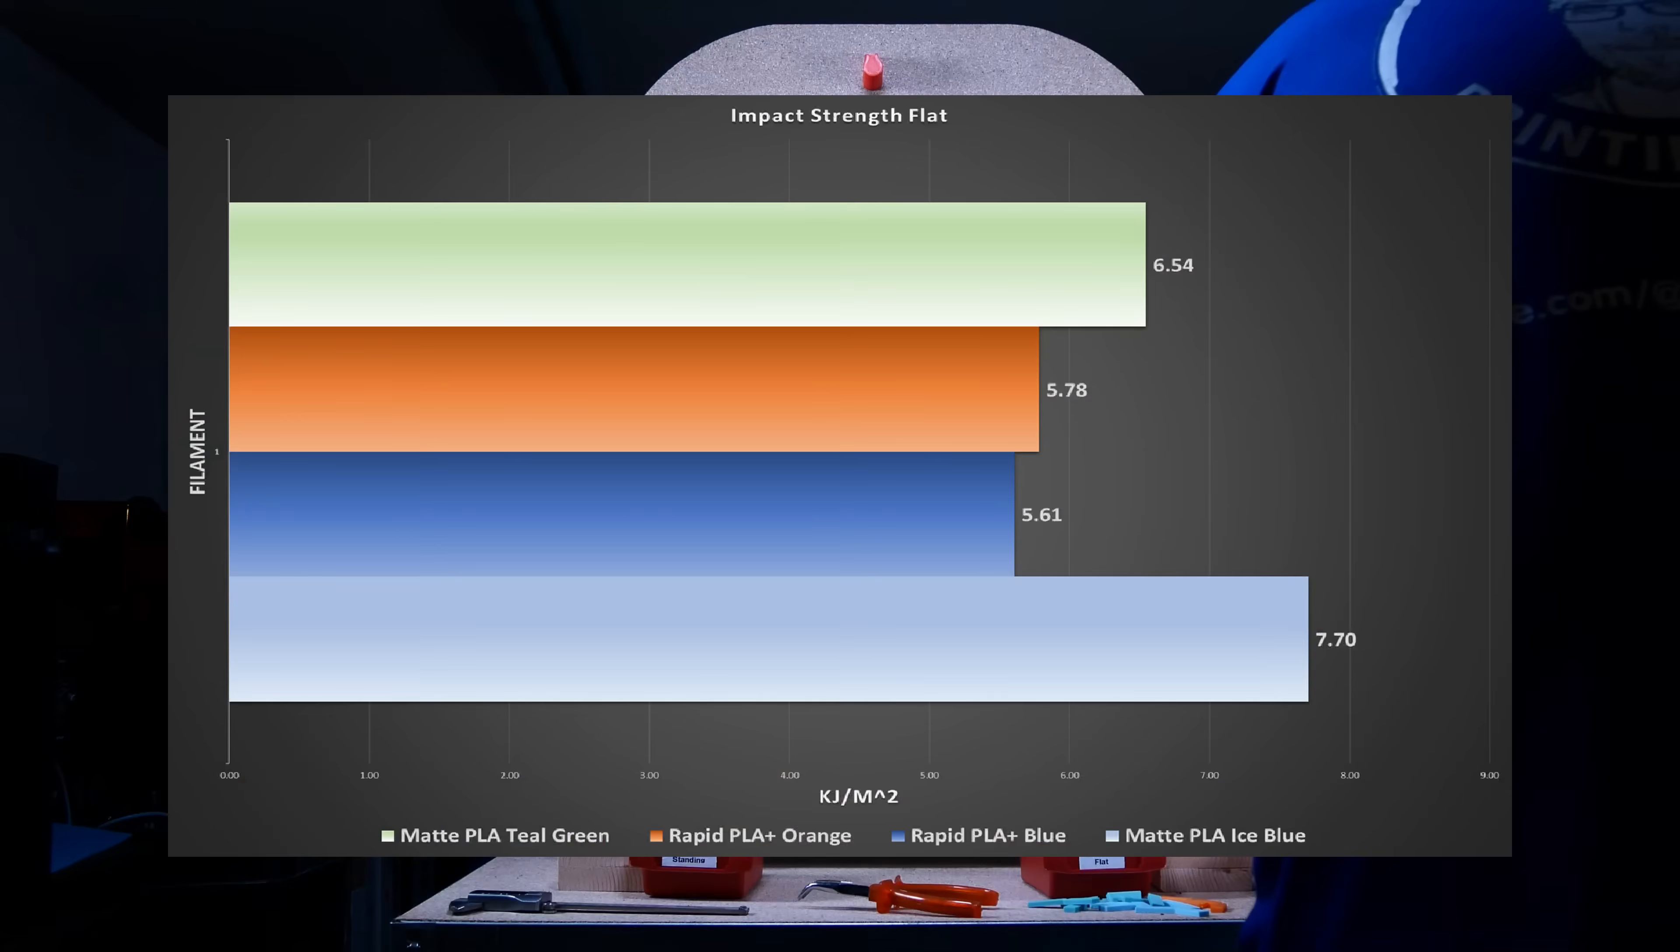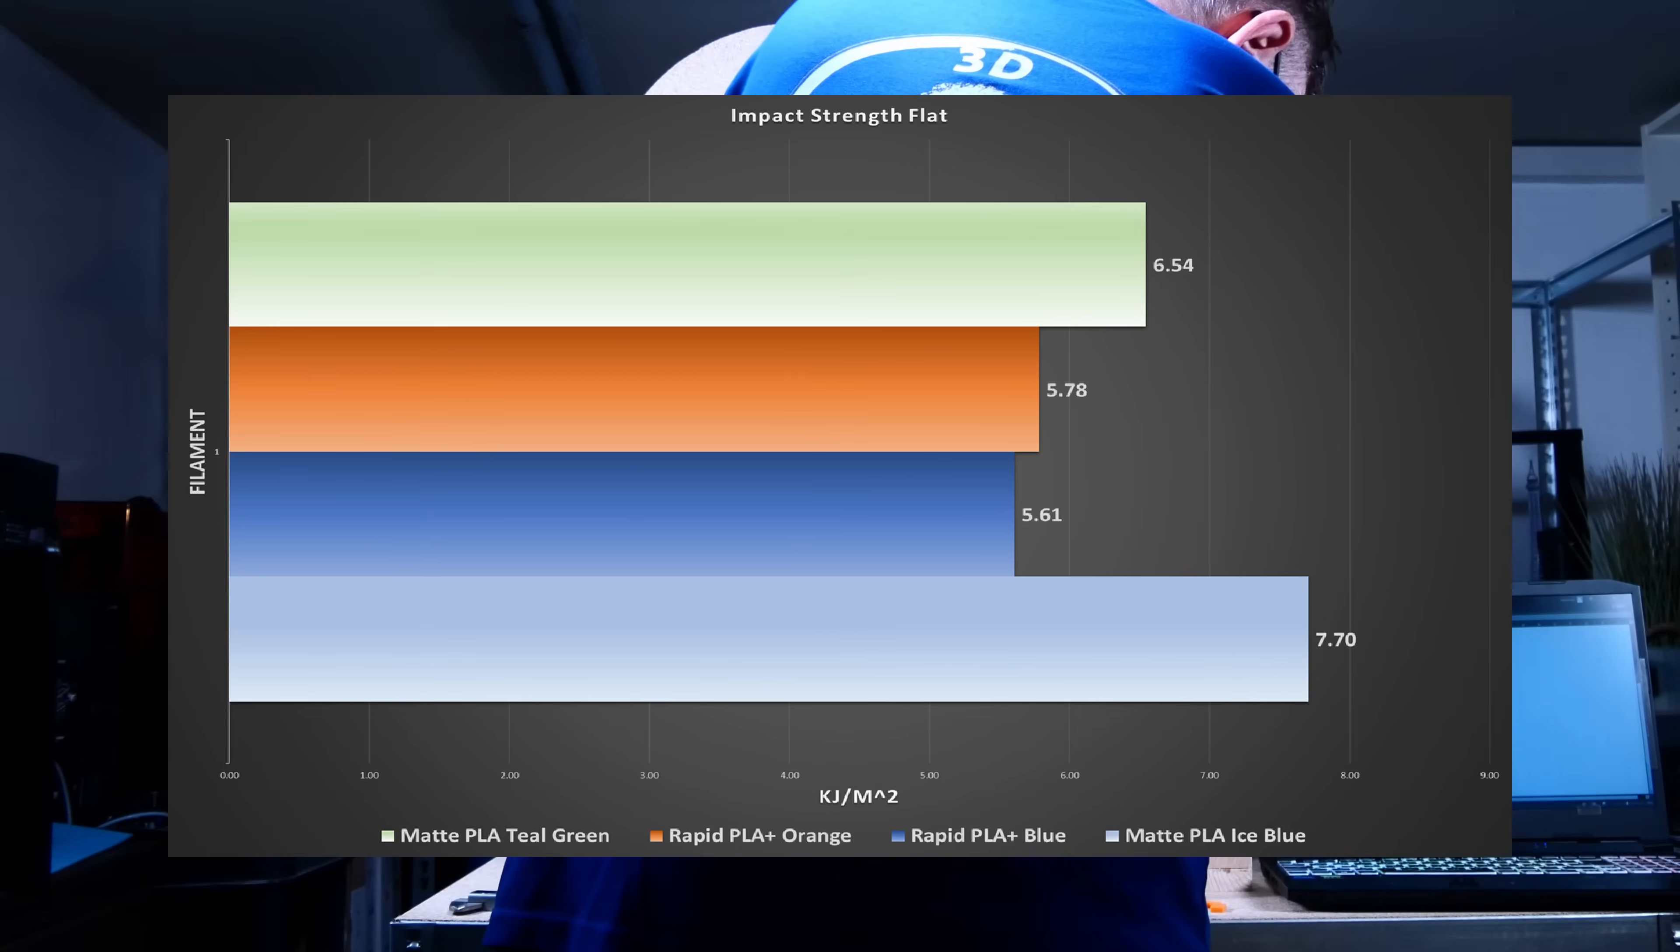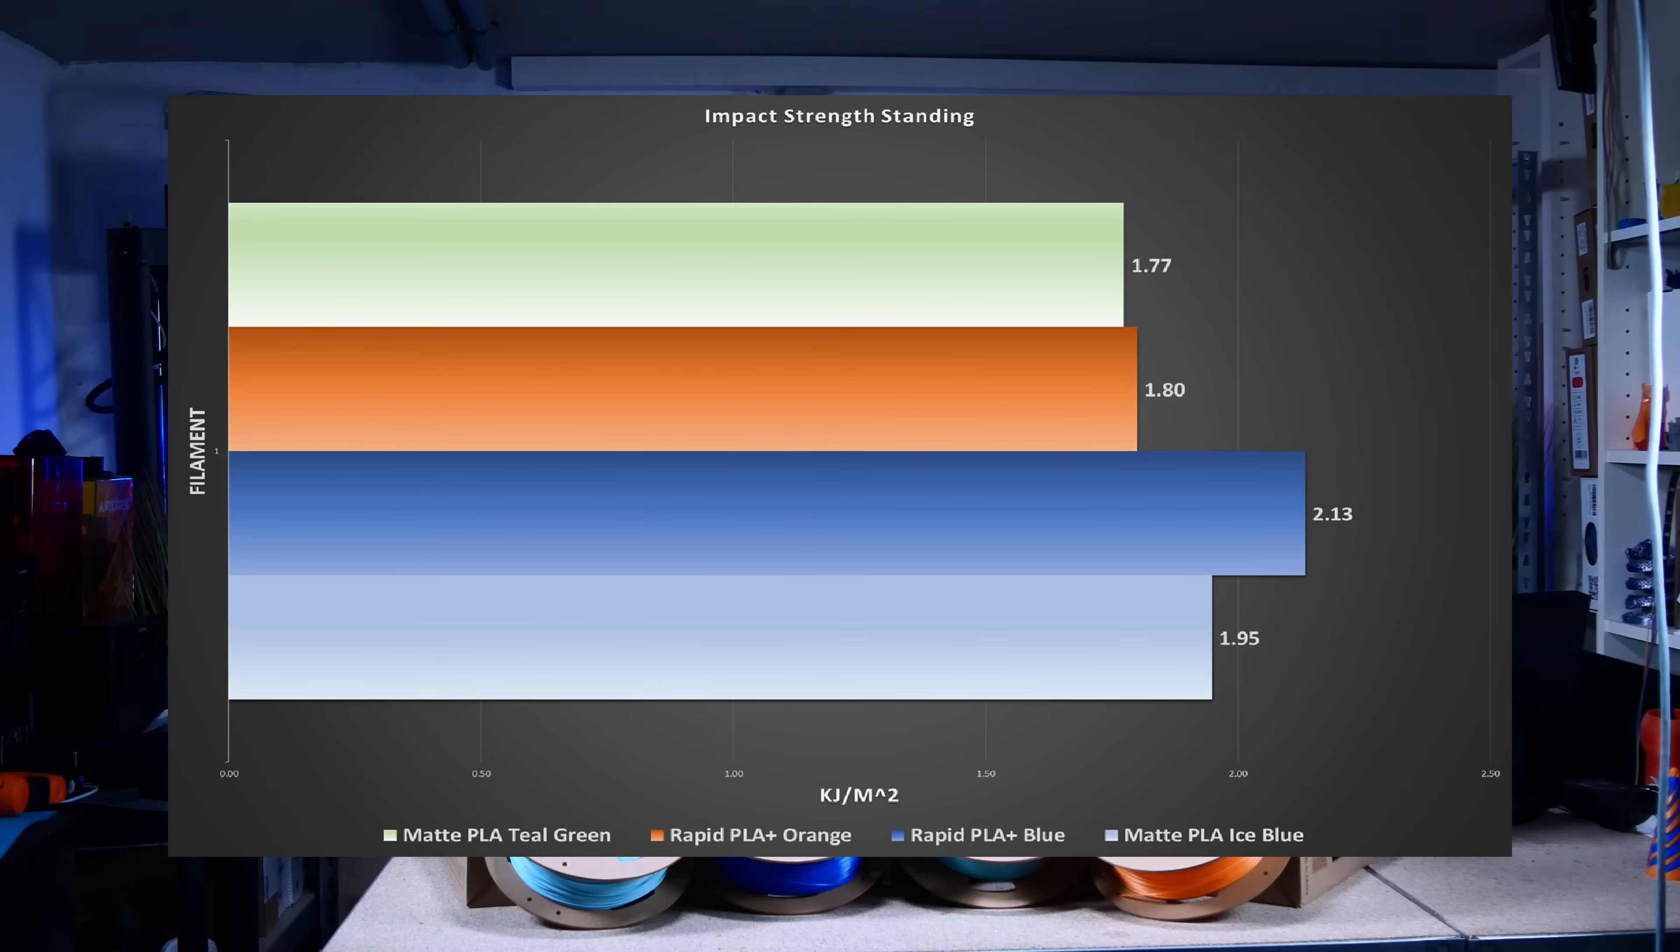I found sources saying that 150 degrees would be better, so I will evaluate that in future tests. Here are the results for the flat printed test specimens. Taking into account that reading the angle from the drag dial is a bit coarse and that the printed test specimens have variations as well, the results look plausible. Two things are noteworthy. The Matte PLA performed better than the Rapid PLA Plus. What is much more interesting is that the filament that performed worst in the diameter tolerance measurement performed best here.